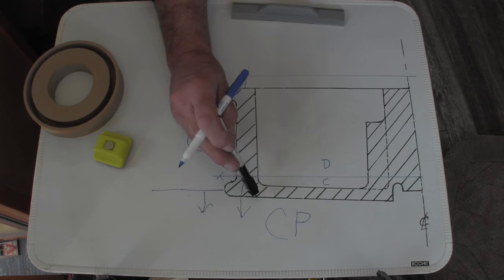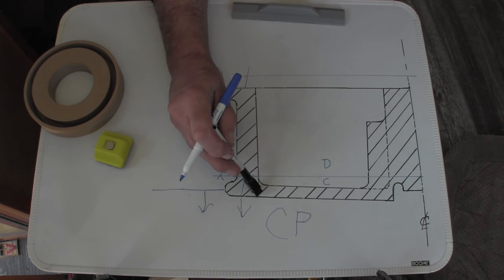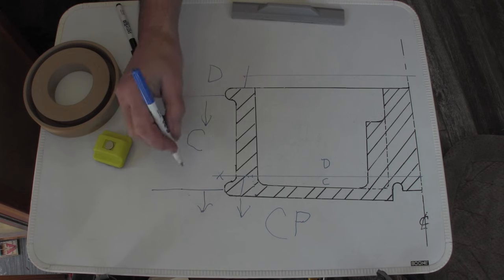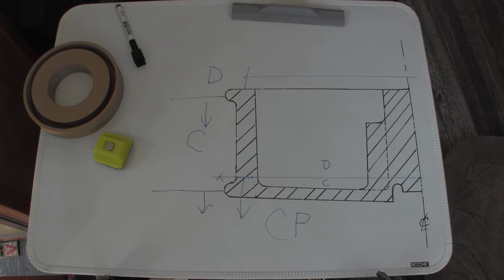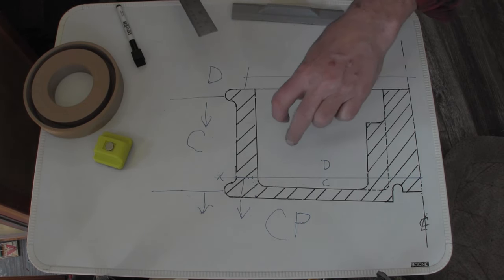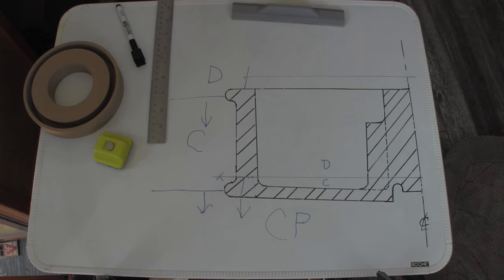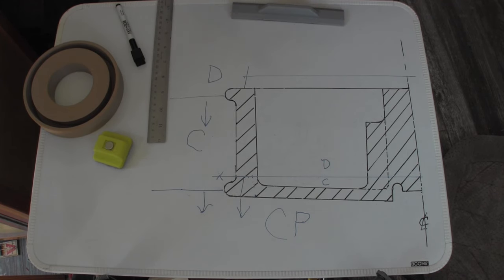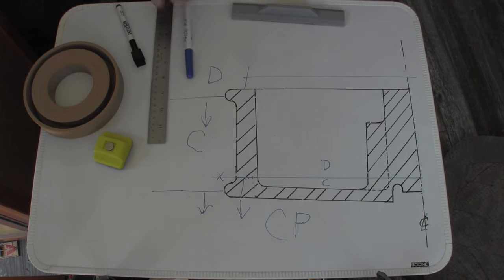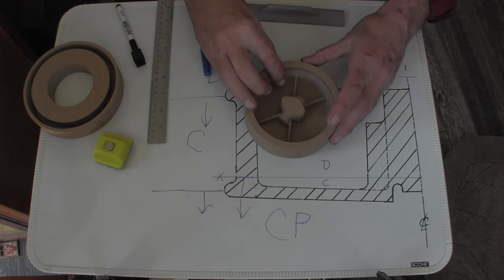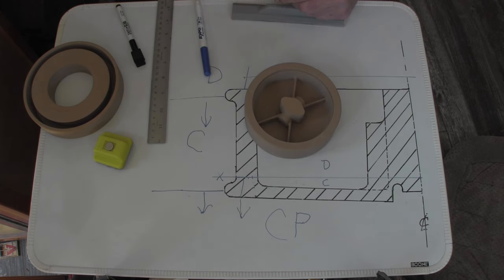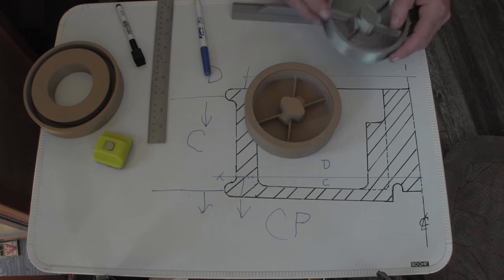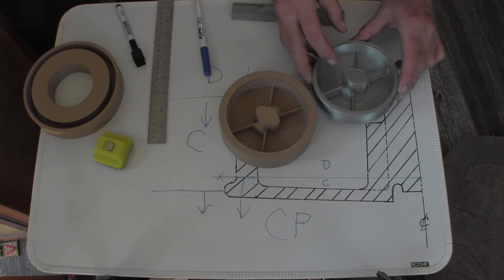Now you've eliminated using a cheek. You've eliminated this outside core entirely. So now the mold size is reduced in size. You make one core that involves this thing, and that core would look something like this. So now you got the core. It's the same as the inside of this pattern.